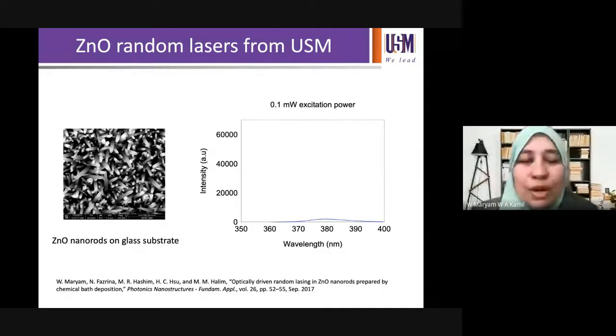So when we brought our samples, it was just a standard zinc oxide nanorod sample. I mean, USM has been doing synthesis of nanostructures for almost 20 years, I think. It's just the application is different. And this time we're bringing this to the application of random lasers. So when we first measured, we saw spontaneous emission, right? Kind of a peak, about 50 nanometer full width half maximum. So this is standard spontaneous emission that you see from any semiconductors. For zinc oxide, it's roughly around 380 nanometers. So this is something that's known.